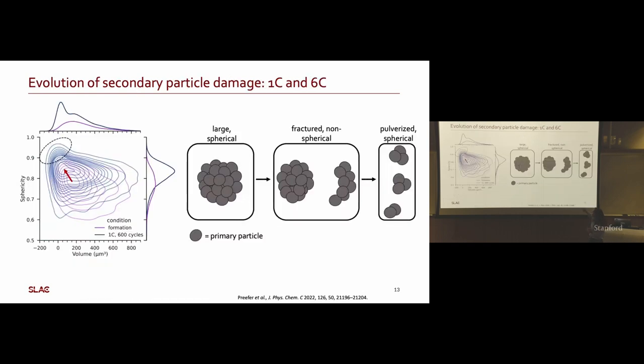And so here, for example, is just sort of summarizing everything. We're starting out with very large spherical particles. We fracture into something that's not spherical, and then eventually it further fractures, further pulverizes into something more spherical. And so in this study, we're able to use the morphology of thousands of particles to track degradation in the cathode and relate that to the capacity loss in the cathode.